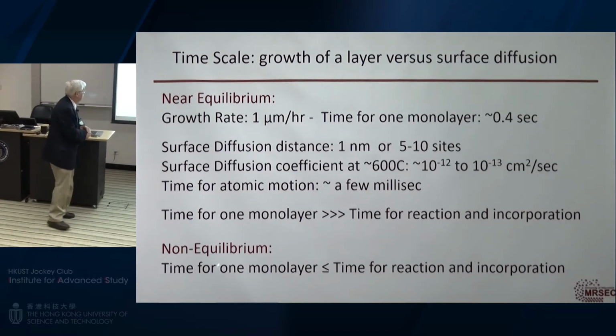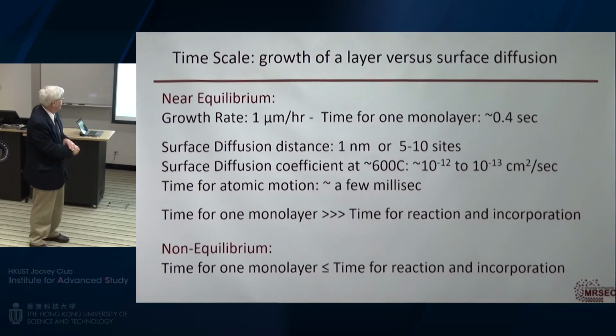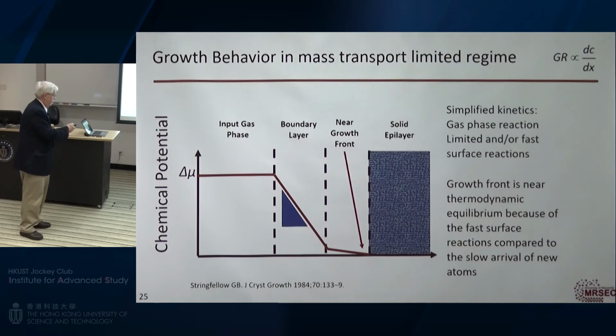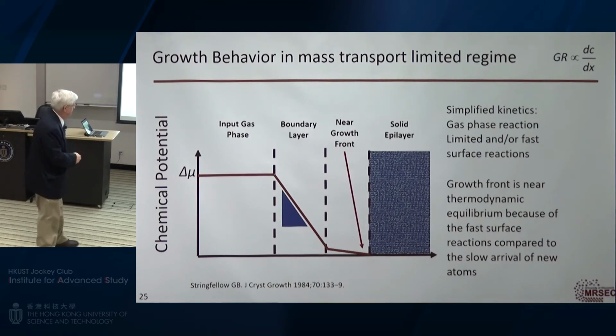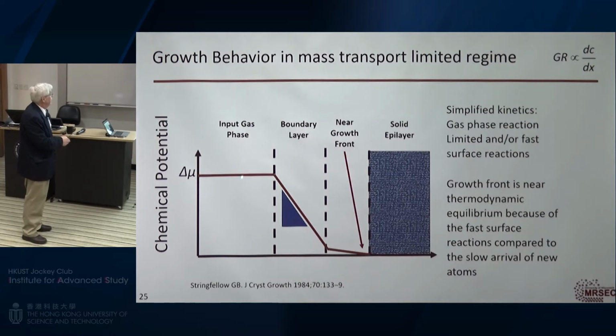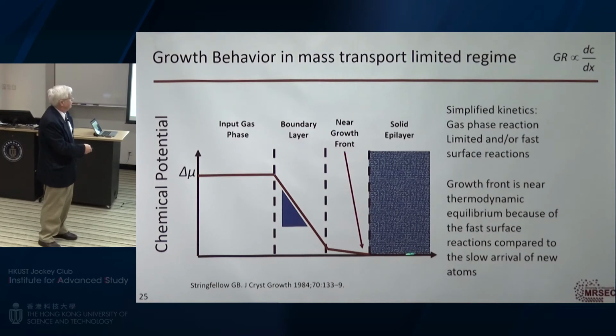If I want to do something out of equilibrium, the time for one monolayer has to be much less, the opposite of this, than the time for reaction and incorporation. And so we're going to go to non-equilibrium conditions in order to do that. And we can kind of see this in terms of a model of an epitaxial growth system. And this could also be of a solidification process, where I have the chemical potential, or the change in free energy with the chemical composition. And I look at this, and if it's near equilibrium, all the atoms will be used up at the surface and get incorporated. And so the growth rate is going to be proportional to the flux of atoms to the surface. And it's slow. And so I have very fast reactions. The atoms can move around on the surface compared to the slow arrival of new atoms.